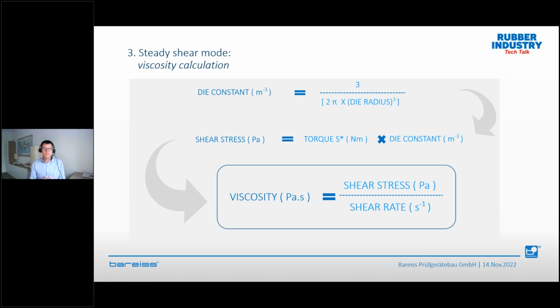Another very important message, what I want to say, another opportunity to measure viscosity is a high pressure capillary. But when I'm discussing with these guys, everybody's telling me, oh, he's doing a lot of corrections, so I'm not a friend of all these corrections. Because what we are doing here, we have the die constant of our cone rheometer. We are measuring a torque. We multiply it with this die constant, so we have the shear stress. And then we take the shear stress, divide by the shear rate, and we have the viscosity. Done. No correction. These are really measured values, only calculated with the geometry factor of our die. So there's no corrections needed.